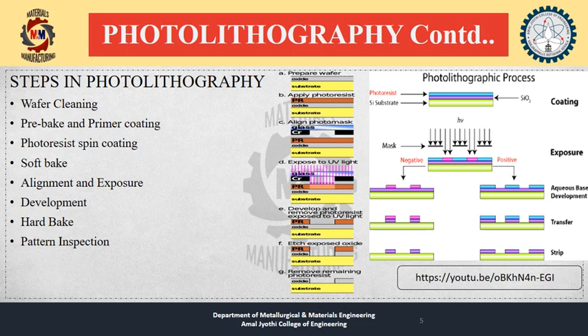For photoresist spin coating, the wafer is covered with photoresist by spin coating. The top layer of resist is quickly ejected from the wafer's edge while the bottom layer creeps slowly radially along the wafer, removing any bumps or ridges and leaving a very flat layer. Film thickness is also determined by the evaporation of liquid solvents from the resist. For very small dense features — less than 125 nanometers — lower resist thickness less than 0.5 microns is needed to overcome collapse effects with a high aspect ratio. Typical aspect ratios are less than 4:1.